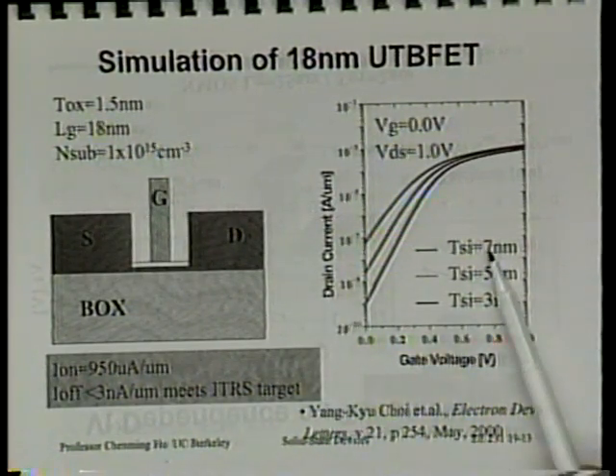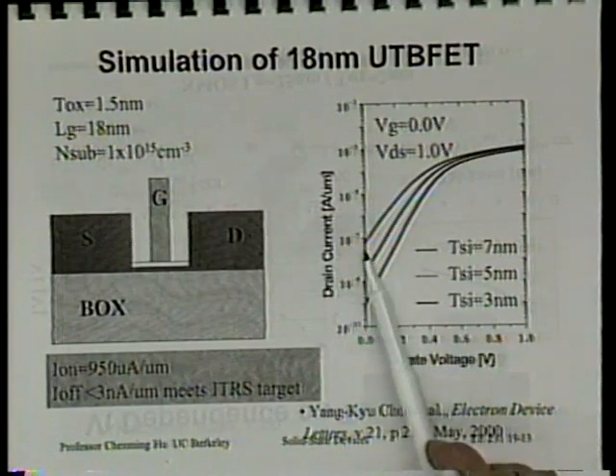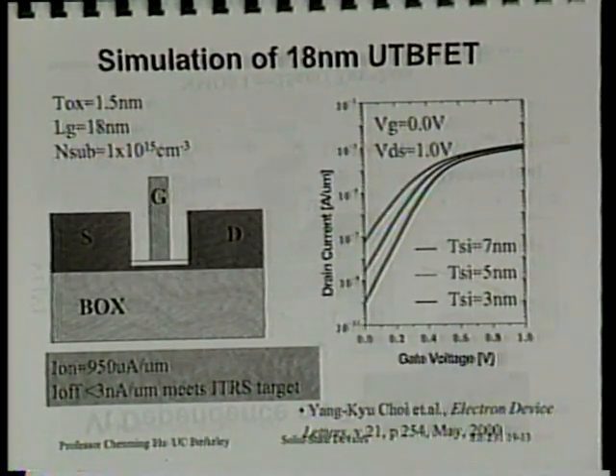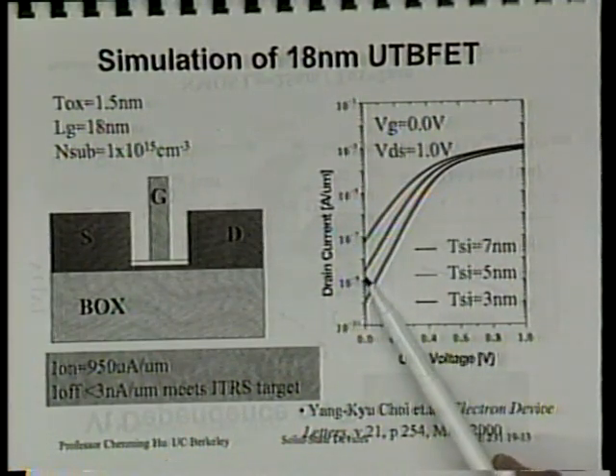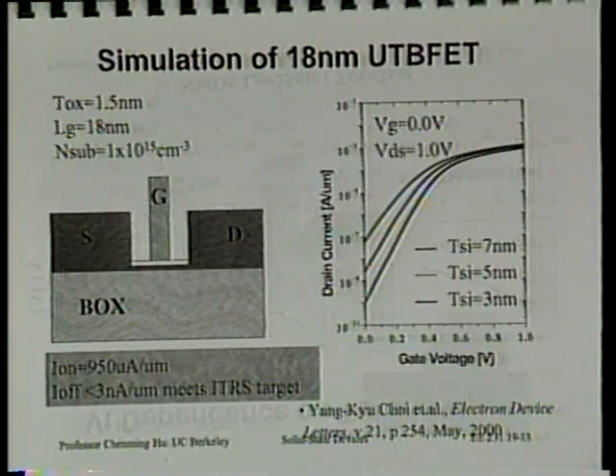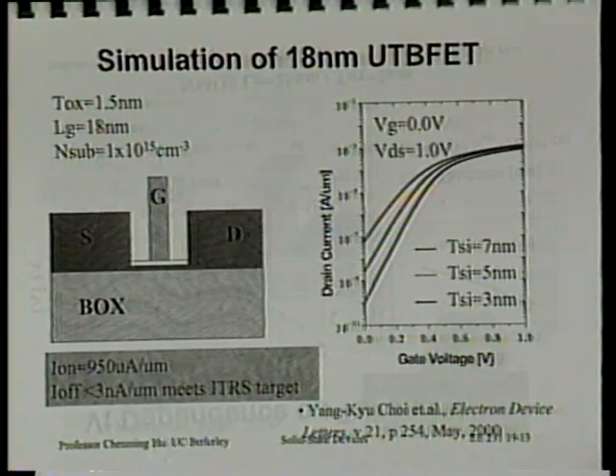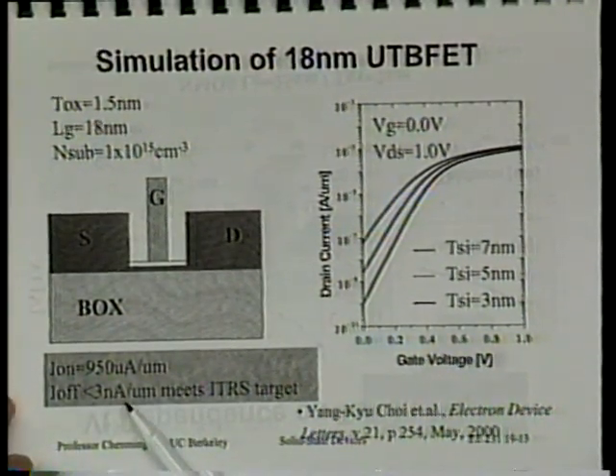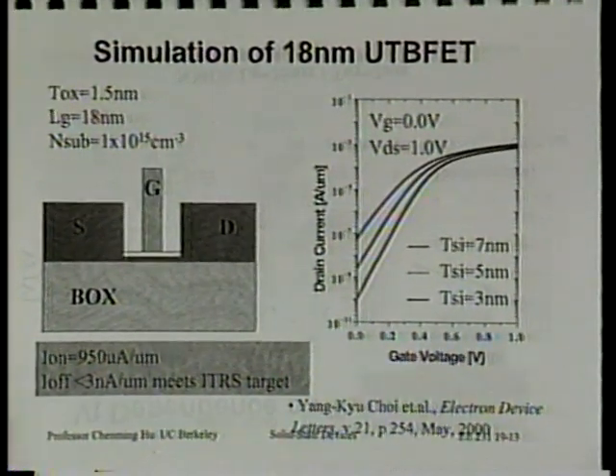we can see it works quite well. Depending on the silicon film thickness, you can get close to, let's say, 80 nanoamp per micron of leakage current, which actually is accepted by the roadmap now for high performance technology. If you use a thinner silicon film, you can see how dramatically it reduces the leakage current. See that? So this is the way to beat the scaling problem through novel ideas of the transistor structure. And here from simulation, we can get 950 microamp per micron of current, and I-off can be very small, right? Okay.